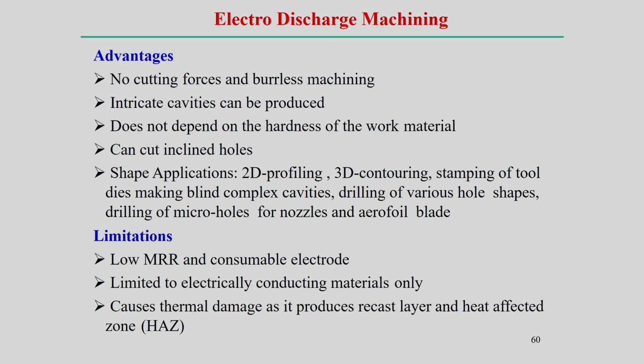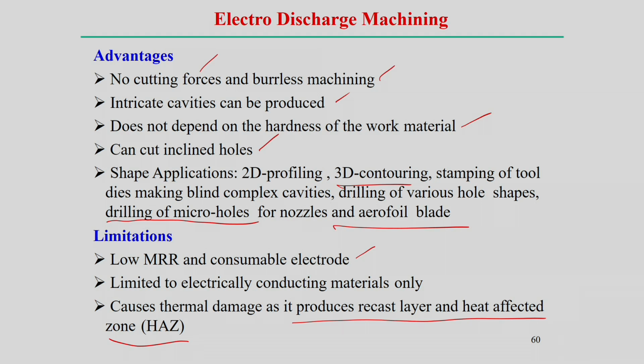If we look overall at the advantages and disadvantages of the electro discharge machining process: no cutting forces happen, it is a burr-less machining process, intricate cavities can be produced by this process, and it does not depend on the hardness of the workpiece material, that is well known. It can cut inclined holes. Different shape applications are possible, like 3D contouring, stamping, drilling of different types of holes and shapes, even drilling of micro holes for nozzles and aerofoil blades. We can apply electro discharge machining very precisely in these cases, but the main limitations are the material removal rate and the consumable electrode, and it is limited to electrically conductive materials. Of course, it causes thermal damage, producing a recast layer and heat affected zone. That is the main limitation of the electro discharge machining process.